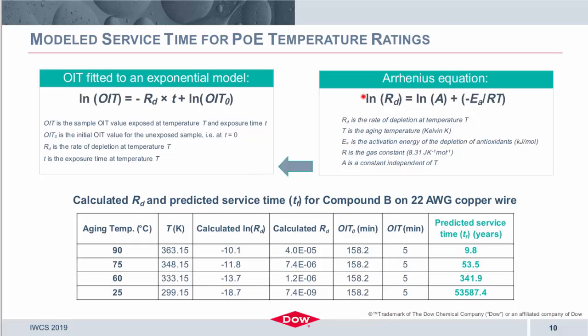Now, in this case, we're taking that natural log of RD and that rate and calculating it out now for the aging temperatures or rated aging conditions that would be typical in the marketplace. So where today's cables are generally rated 60, 75, up to 90 degrees C and beyond now, as we talk about power over Ethernet, we're able to use this model and calculate the different parameters, which ultimately leads to predicted service times under any given aging temperature, where our OIT naught was the original OIT value of the given material